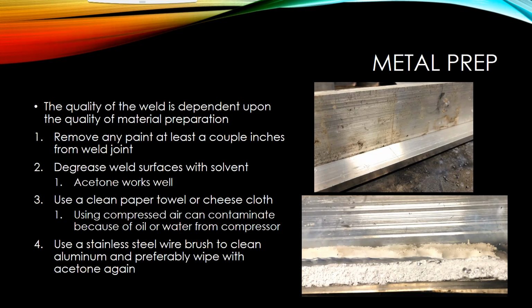So after you've cleaned it off with a paper towel or a cheesecloth, usually what I'll recommend is hit it with a stainless steel wire brush. What's really critical is you make sure that that stainless steel wire brush is designated only for aluminum use. If you go use it on steel, then back on aluminum, you'll draw those contaminants into that aluminum. So make sure that that's designated for aluminum use only. And then after you're done with that, wipe it with acetone one more time.